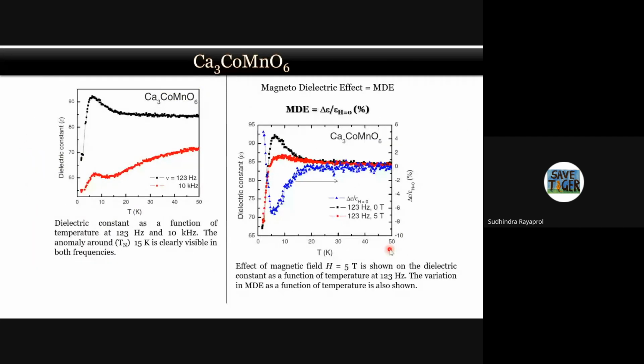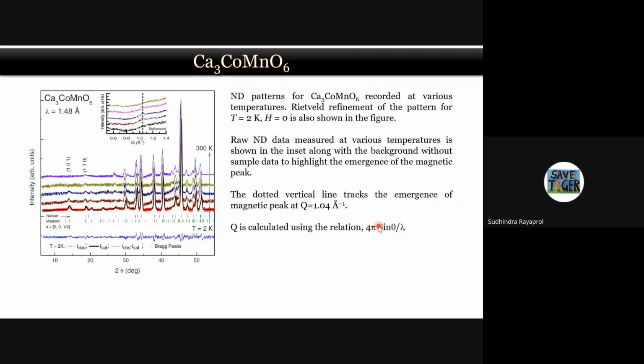But what happens when we apply magnetic field? So we are looking at the magnetodielectric effect. When we apply a large magnetic field, we find that around 7 or 8 Kelvin there is a large change, about 8% change at 8 Kelvin in the presence of 5 Tesla field. So this was something interesting for us.